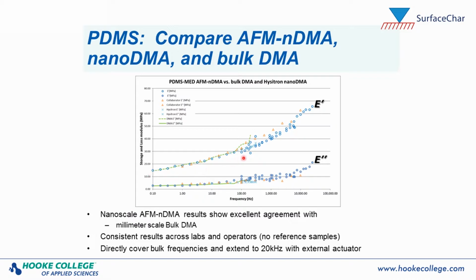as a function of frequency. And so what we can see is if we focus on the AFM nano DMA measurements, which are in blue here, and compare them with the bulk DMA measurements that are the green line, we can see excellent agreement between the millimeter scale bulk DMA and the AFM nano DMA, which is on a length scale of about 10 nanometers. There's also some data in here from a collaborator on their own system in their lab, which are the spots in orange, and we can see that there are very consistent results across the labs and operators for these moduli.